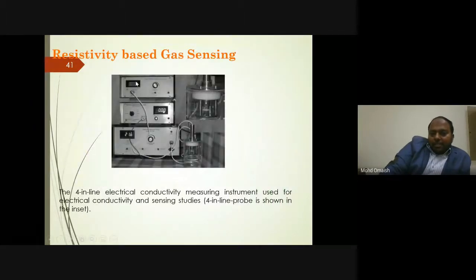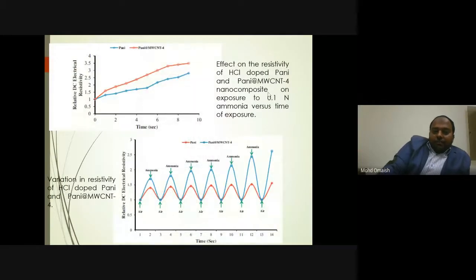Another application is gas sensing. The conductivity or the resistivity is one of the main factors exploited for gas sensing measurement, and a lot of papers have been published on polyaniline using resistivity-based sensors. Previously we used our 4-probe system, but now we have much improved. This is from a very old paper. We got very good results after exposure to ammonia.